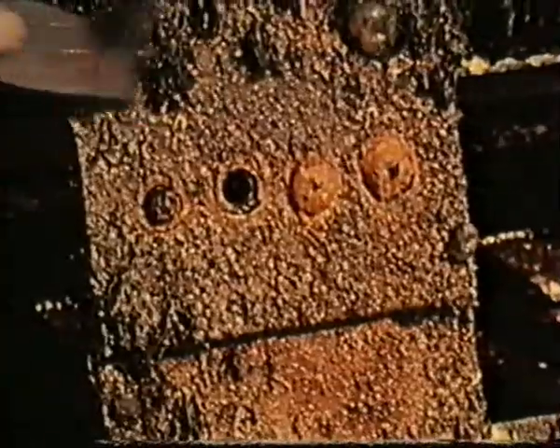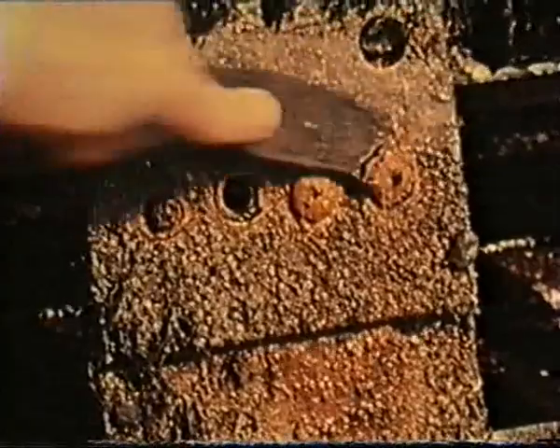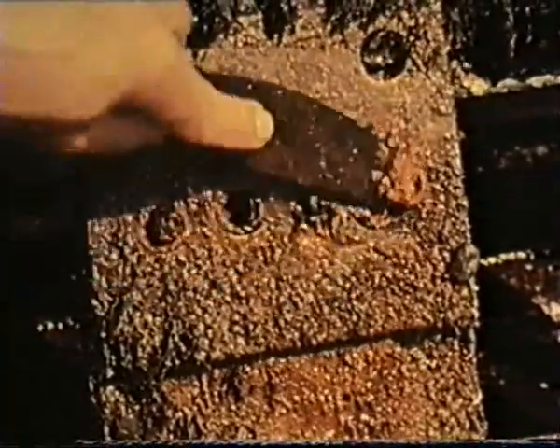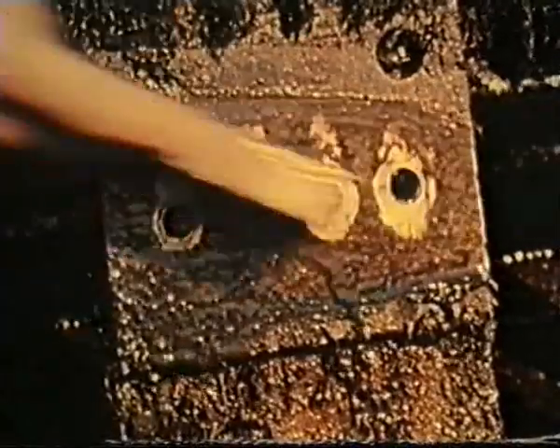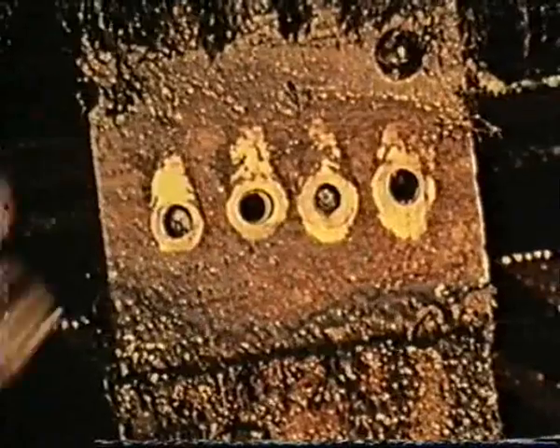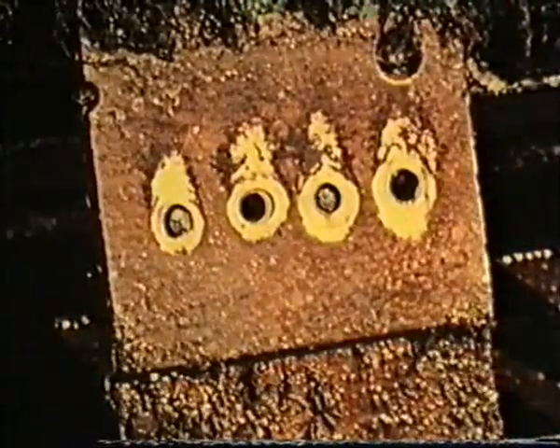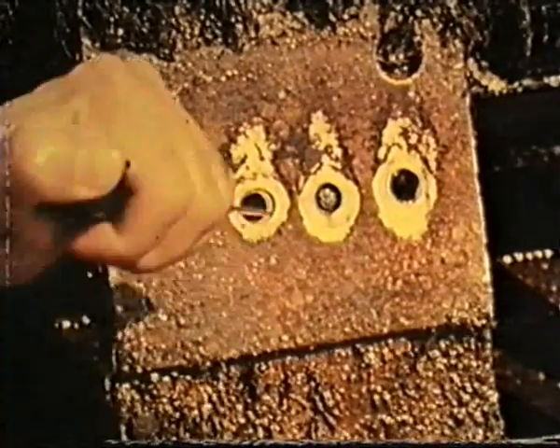Now let us see what has happened to the steel rivets used to join the two copper plates. Here the steel rivets have been attacked very severely. The metals are the same in each case, but the unfavorable area relationship of the large copper cathodes and the small steel anodes was responsible for the severe galvanic corrosion of the steel rivets.